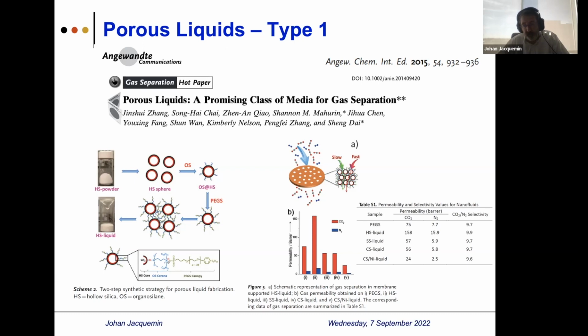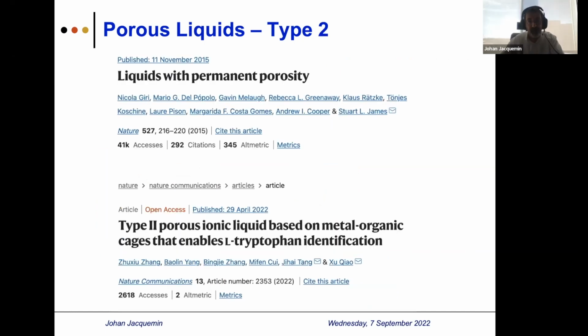I moved to the supporting information to try to get more information regarding how they determined the selectivities. Basically, selectivity was calculated solely from the permeability of the gas, which, from my point of view, is incorrect. They report with different media, including the starting material, and they show that their porous liquid shows very excellent selectivities. Let's move now to other publications for the type 2 porous liquid, and I just want to highlight the importance.